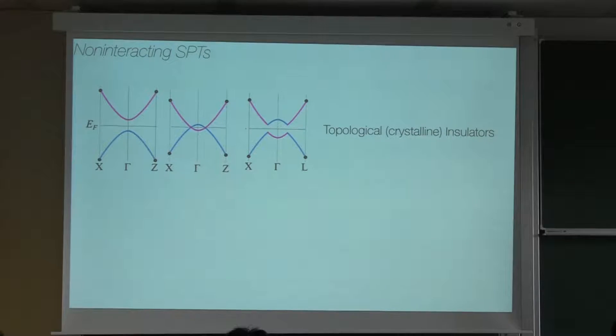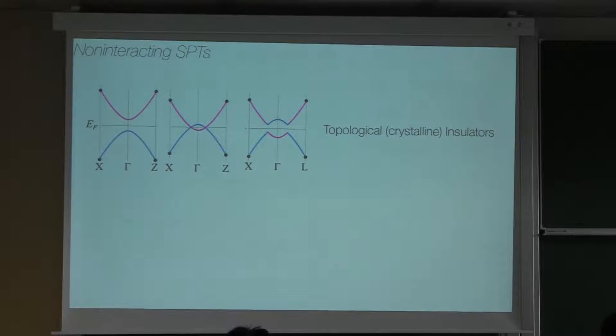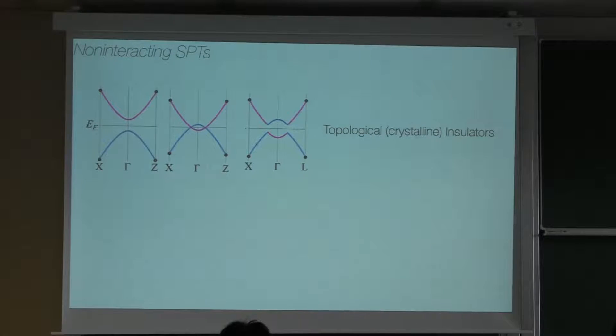When we think about topological materials or topological insulators, these are basically non-interacting symmetry-protected topological phases. One of the most simple ways to think about TIs is to take a semiconductor, have a band inversion of some sort, then use spin-orbit coupling or some other mechanism to open the bands. You can then compare an insulator to an insulator — the electron fillings are exactly the same — but one is topologically non-trivial and the other is topologically trivial.